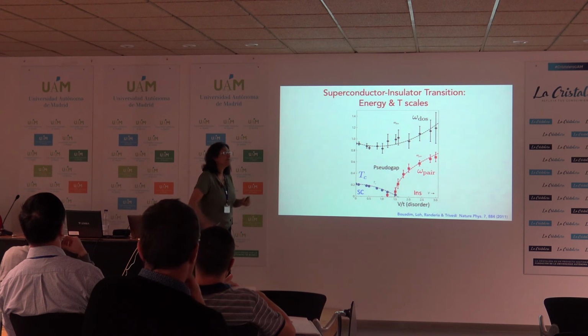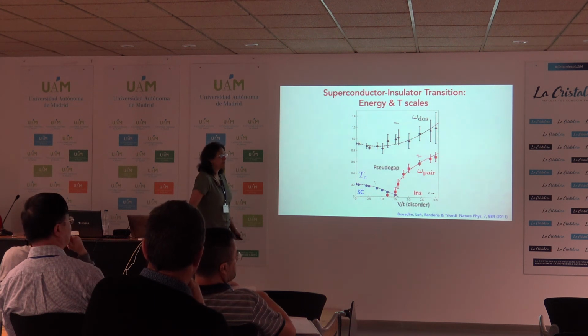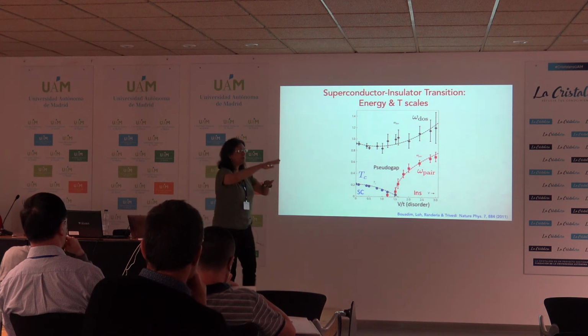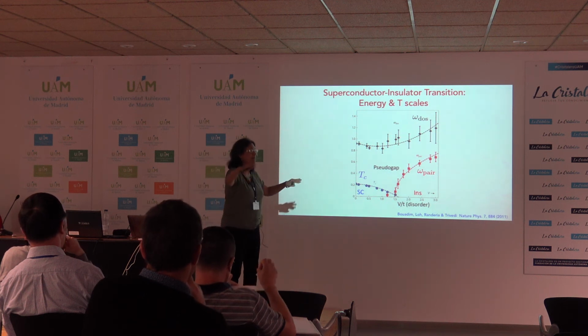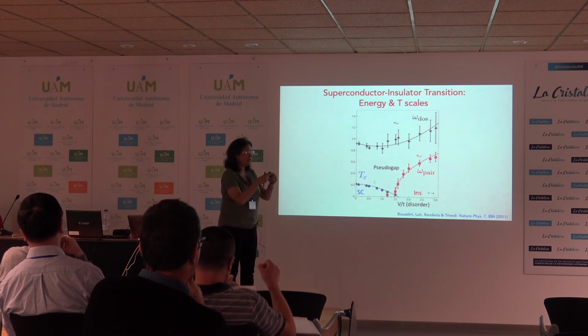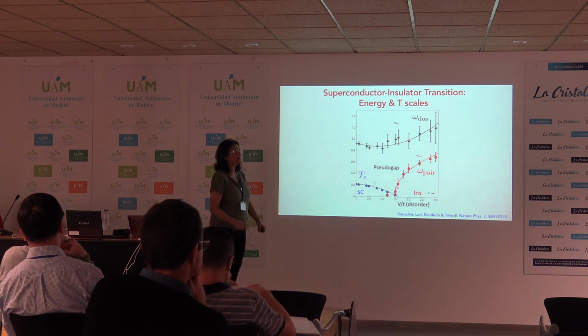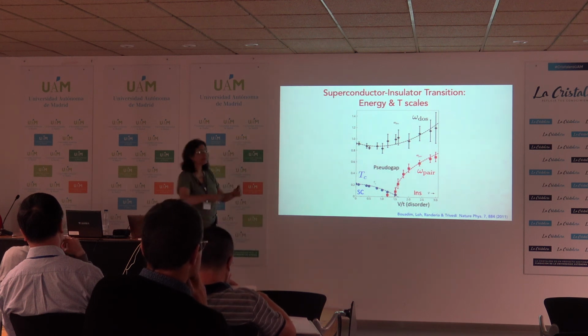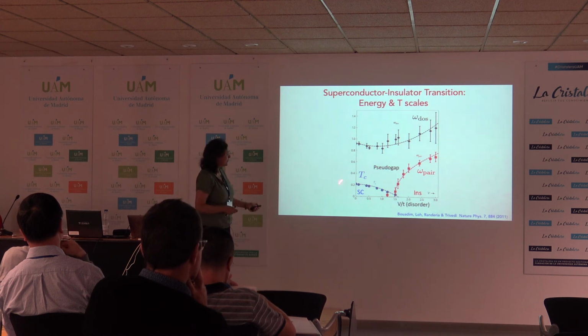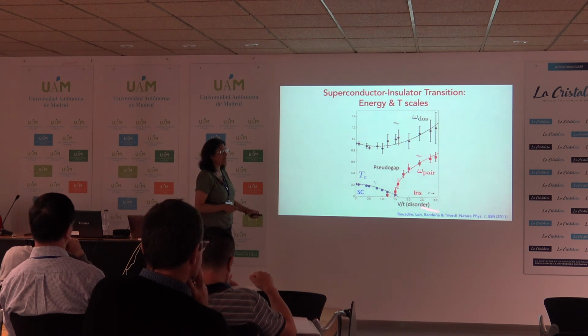So that requires phase coherence, right? So if you're in this region, you're saying within your patch, you do not have phase coherence? Within the patch you do. But the Fraunhofer pattern was ultimately averaged over the whole system, so you're not just doing a Fraunhofer pattern within the patch. So you need multiple patches and long-range phase coherence, which exists only here. Here you don't have long-range phase coherence.